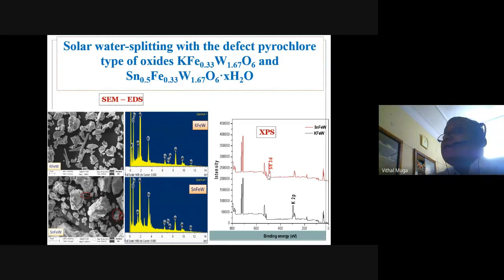Now you look at the XPS of this. Now you look at KFEW. It does not contain a tin peak. But the tin peak comes here. Now please notice this. This is one characterization technique showing that the ion has gone into the solid. But this is not the only characterization technique. We have other techniques also.